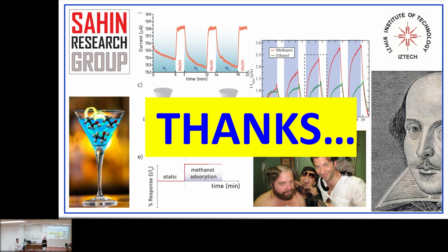Thank you, Hasan. Just one question. The way you perform this experiment, you have your printed electrodes and then you just drop the ethanol or methanol directly, diluted or not diluted, or in a chamber with pressure control or not, because of the evaporation. There's no pressure control and no dilution. I'm asking because of course you will have an equilibrium between the molecules in the gas phase and the molecules in the liquid until it evaporates. And the polarizability of these molecules may change if there is water in the ambient.